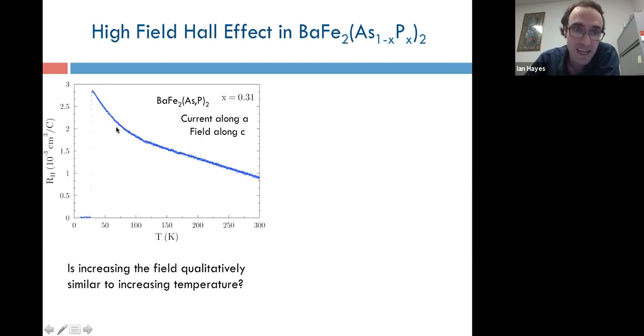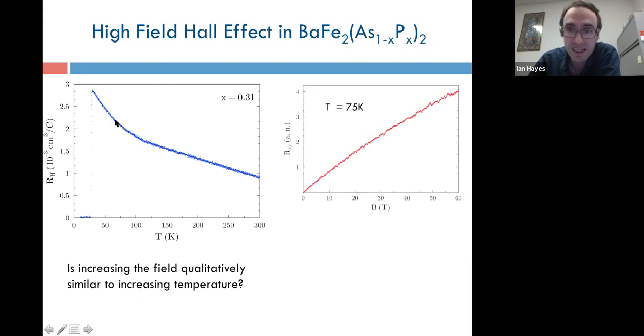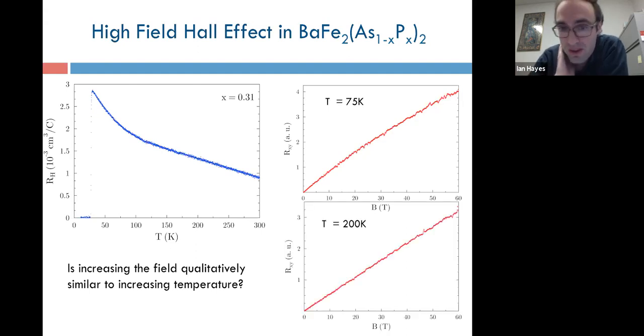And so the question we'd like to ask, is there any distinctive field dependence in that region? So if you go to the middle of that upturn, somewhere around 75 Kelvin, and measure Rxy, the off-diagonal resistance as a function of field, you'll see that it's actually sublinear. So if you were to define an effective Hall coefficient at each field, that's Rxy over H, say, then you would actually see it's decreasing with field, qualitatively similar to what happens when you increase temperature. And furthermore, this only happens within this low temperature upturn region. So if you go up to 200 Kelvin, you get a very straight Rxy all the way up to 60 Tesla.